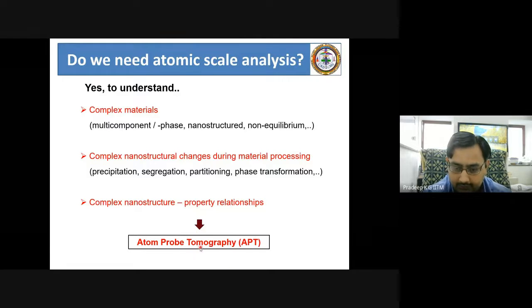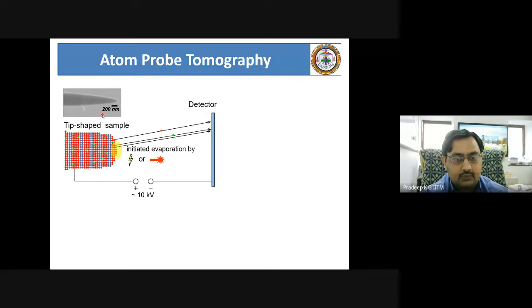Okay, so let me now briefly introduce this technique. As you see from this picture, this technique requires a very sharp nanometer scale needle. You can see the sharp needle obtained from a transmission electron microscope, which has a diameter of, let's say, 50 nanometers over a length of possibly a micron. Now, on this sharp needle of the sample of your choice, we are going to apply positive potential. And when you apply positive potential, the atoms at the apex of the tip get strongly polarized. Or, in other words, the polarized atoms can be triggered for field evaporation.